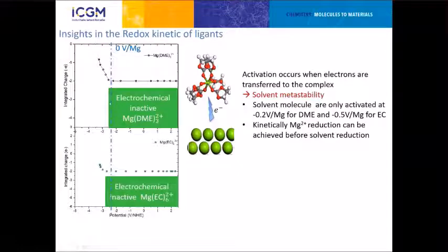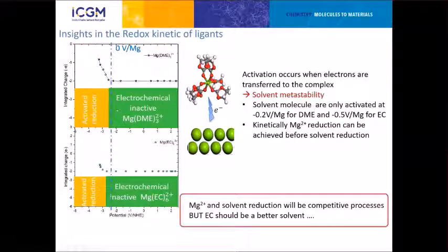So it gives us the electrochemically inactive magnesium 2+, and when electrons start to be transferred, the solvent reduction starts to activate, giving the active reduction zone, where certainly all the dimerization and fragmentation are going to happen quite fast. The blue line is the potential of reduction of magnesium. What we observe is we still have a very small zone, about 100 millivolts, where we can get an electrochemically inactive magnesium in DME. But this electrochemically inactive DME will quickly go into the reduced active zone, so we are going to reduce both magnesium and the solvent.